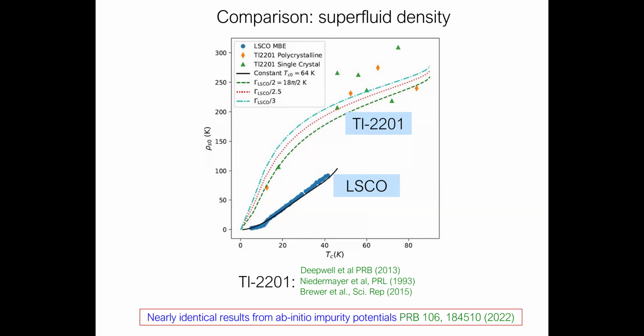Then there was some criticism that these impurity parameters were kind of ad hoc. They were just fit parameters. So we worked with Tom Berlijn at Oak Ridge to calculate these impurity potentials from first principles. And these are oxygen vacancies and strontium dopants and thallium substituting for copper in the thallium system, or copper substituting for thallium, excuse me. And it works pretty much exactly the same. And that's in this paper down here in 22. I don't really have time to go into that story either.